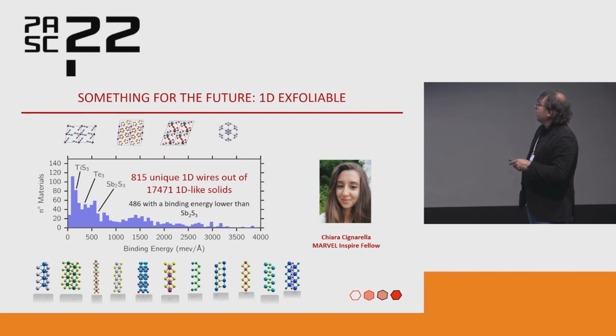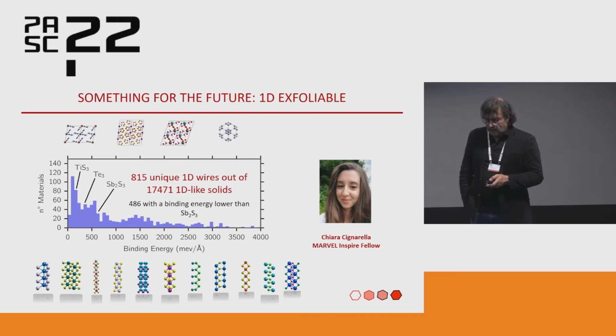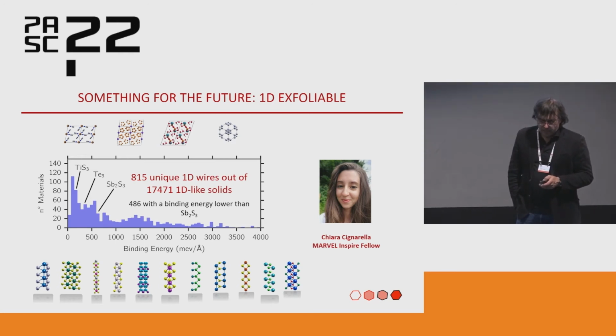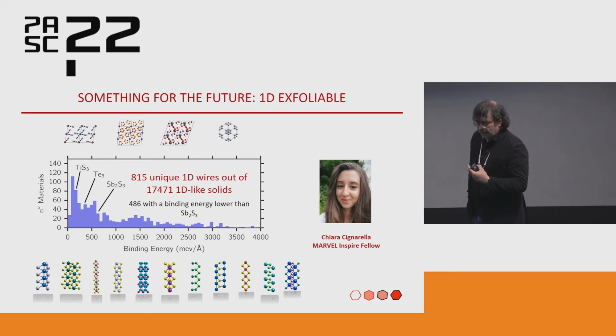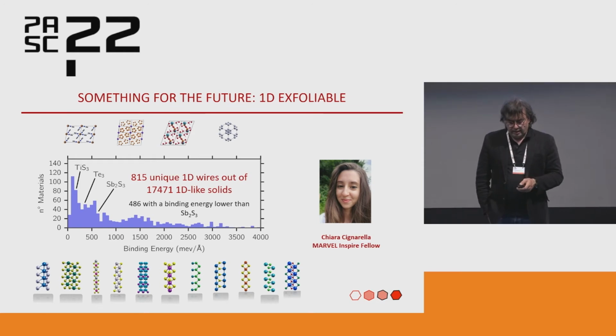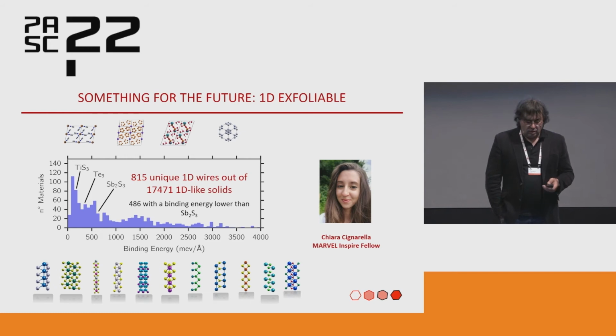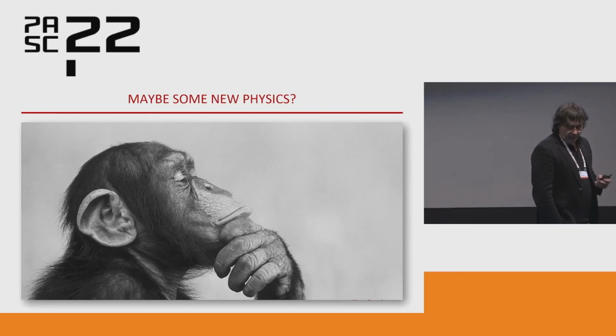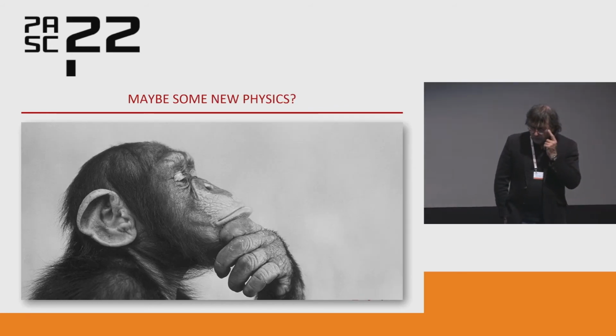giving us finally materials that have a clean structure where we can look for a large density of states for interconnects or vias, that is, being able to bring a lot of current to our chips, or materials that are semiconducting and can be field effect doped, exactly giving us what the nanotubes should have given us, but without having to worry about not having a well-defined band gap.